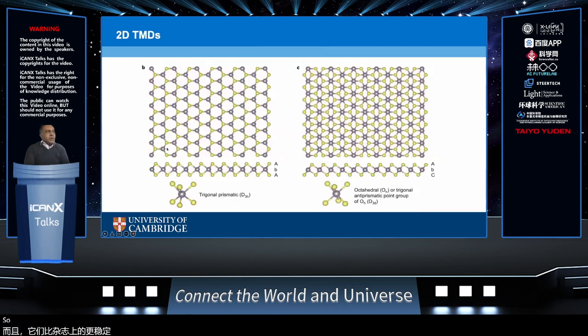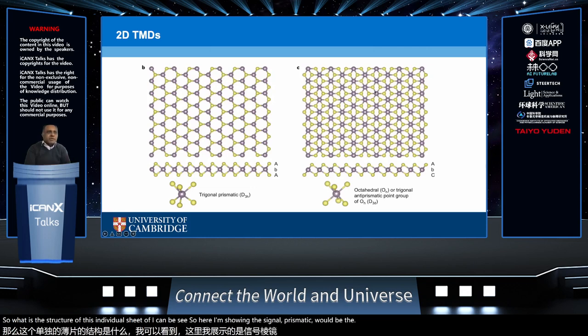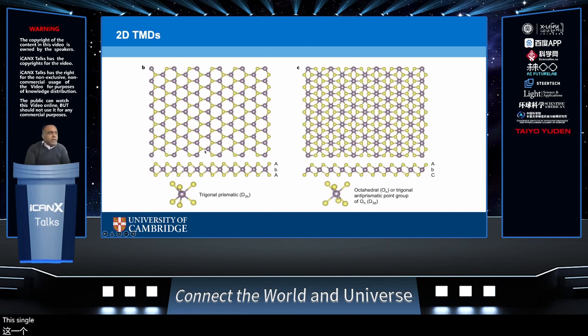So what is the structure of this individual sheet of TMDC? Here I've shown the trigonal prismatic, which is a semiconducting phase, and the structure of the octahedral, which is the metallic phase. If you look at the MoS2 sheets from the top, they resemble the hexagonal structure of graphene that we're all familiar with. But if you look at it from the side view, we see that this single layer consists of these three atoms, as I mentioned before.